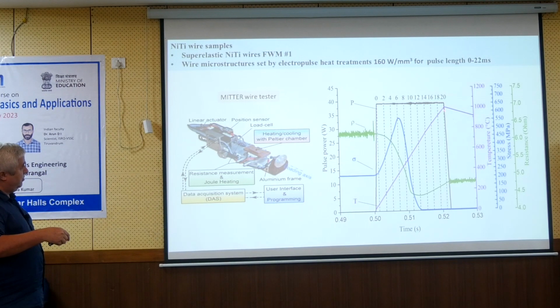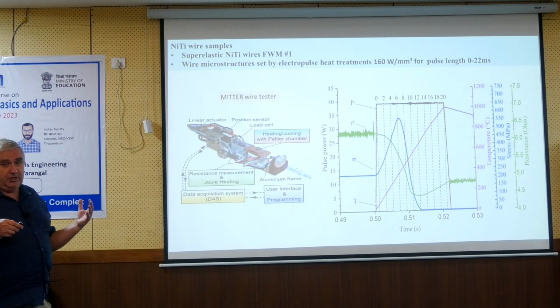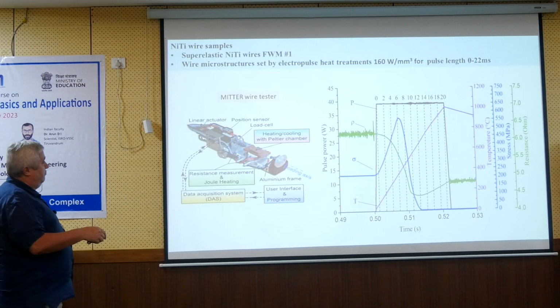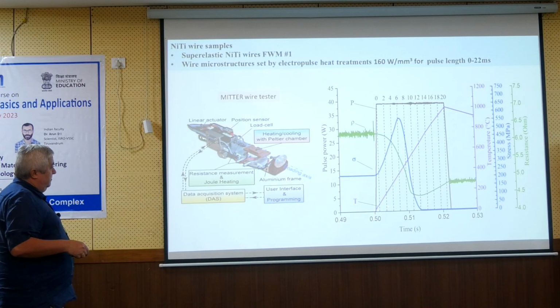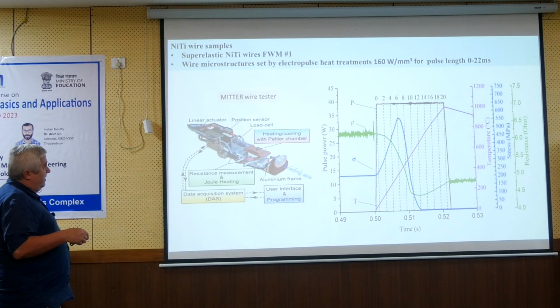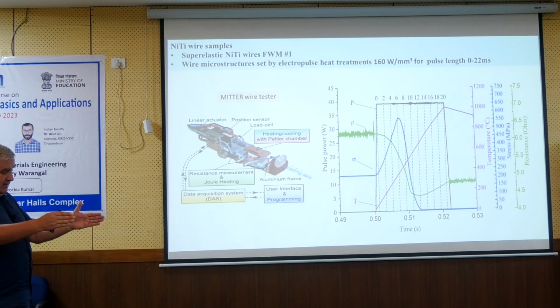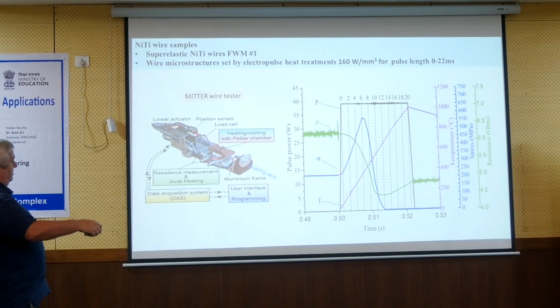By adjusting this time, you perfectly control the maximum temperature which you reach. The material microstructure is controlled by this maximum temperature. So by this electropulse treatment, we can prepare a wire which has different microstructures depending on the pulse time. And because we are doing it by electric current, we can measure it in the testing system. We take the wire, fix the length, and then send the pulse. When we send the pulse, we can observe the stress.